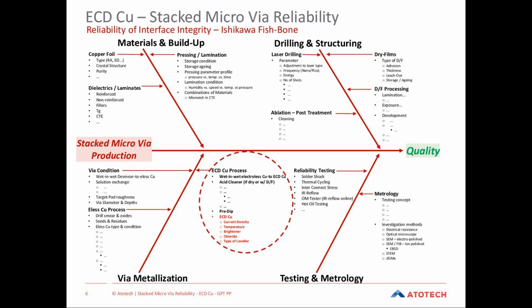So the leveler itself is for sure the main additive causing adsorption of organics on interfaces. On the other hand, it also depends on the brightener, how much a brightener can work against this adsorption of leveler chemistry. That means here we have a competitive situation between additives. And when you change a leveler, it is also possible to change the brightener and to take a look if this combination at the end also works well together.